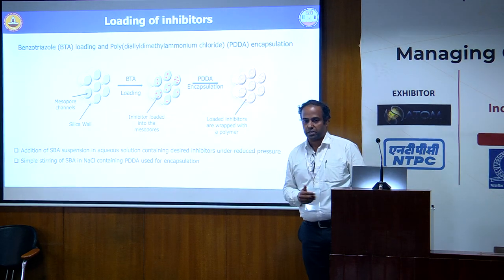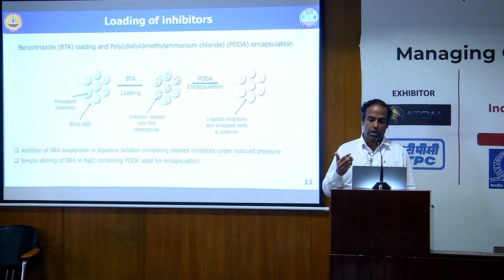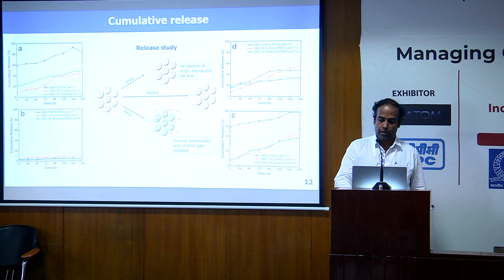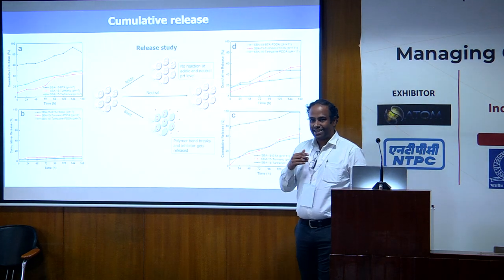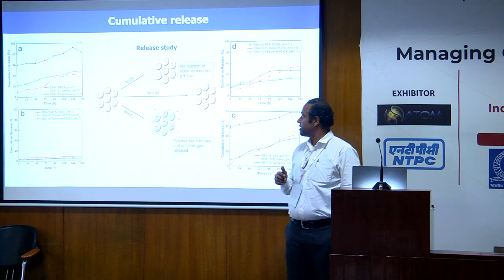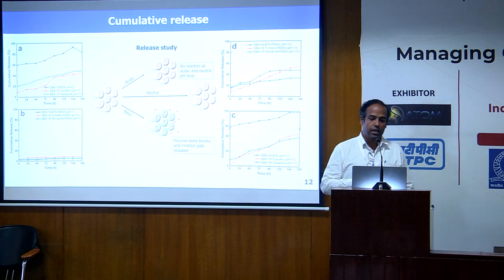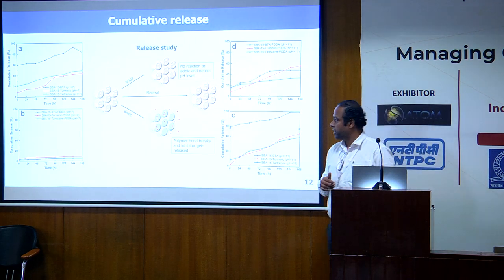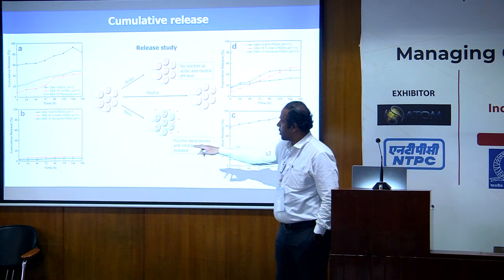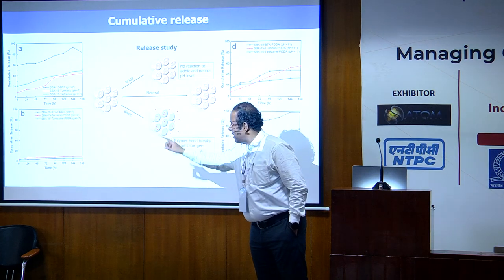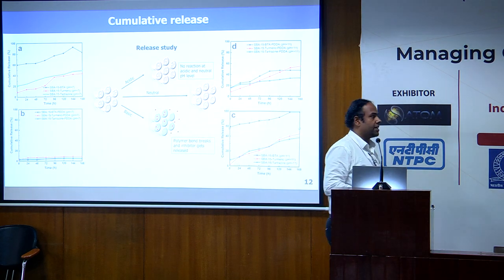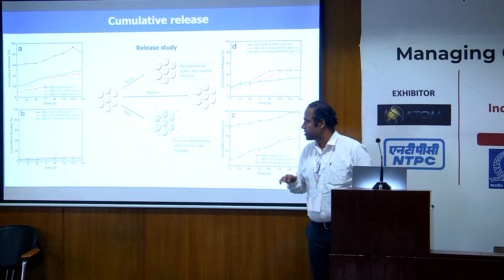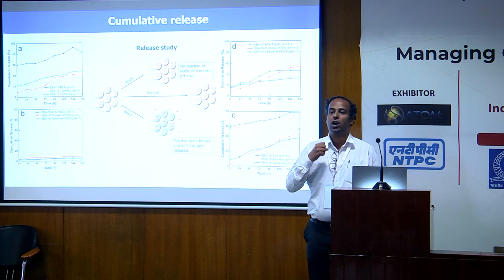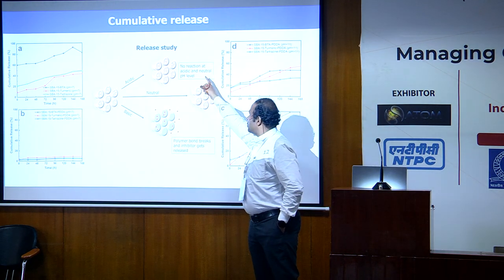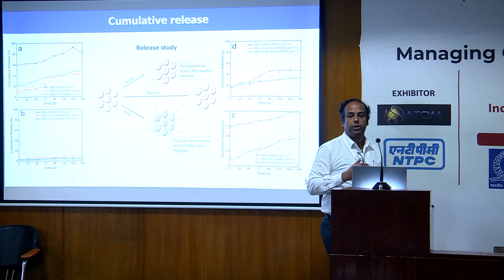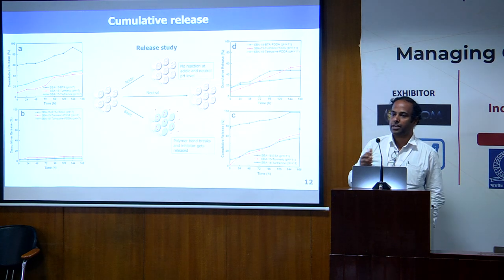We performed XPS characterization to prove that the molecules are present, and then we tried to see, does it release first of all? So we tested release studies using UV-vis. The left image is for pH 7, which you see at the bottom. At pH 7, when you are encapsulated with PDDA, the cumulative release rate is much, much lower, or it does not open up. There is no reaction at acidic and neutral pH because your PDDA is insensitive at that pH.